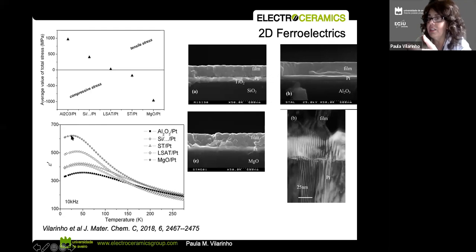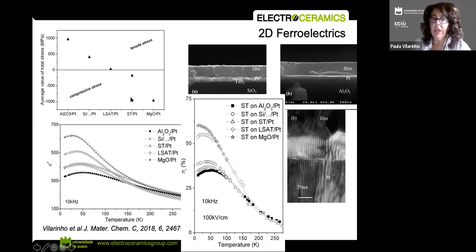So my example here is, okay, when we decrease the size of materials, we face a lot of difficulties. However, when we decrease the size of materials, we can engineer the material to a certain level. And that's what I'm representing here. I don't have time to go into details, but strontium titanate is really an important material in terms of tunability. This means I can tune the dielectric permittivity by using an electric field and by using the temperature. So again, here I can see the highest tunability of my films is associated with the films deposited on magnesium oxide, those that are more compressive.